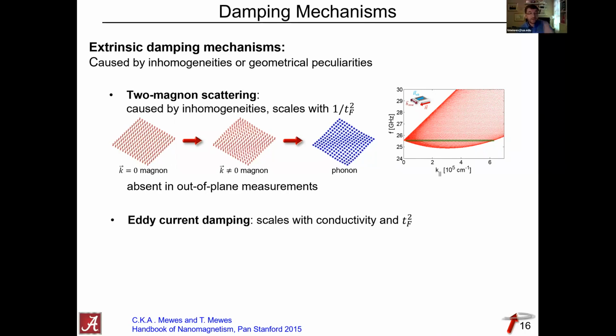Which brings me to another damping mechanism, which is eddy current damping. Eddy current damping is just that: the precessing magnetization causes eddy currents, which in turn lead to dissipation. Again, the interesting part here is that for thin films you expect this to scale like the film thickness squared. So you make your films thicker, you get more eddy current damping. And so that's a handle that you have experimentally